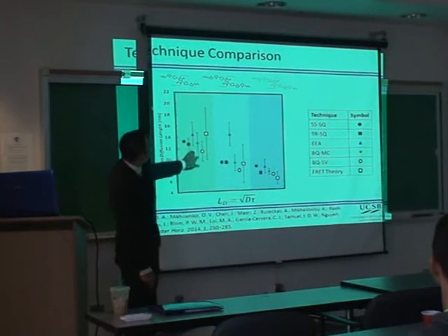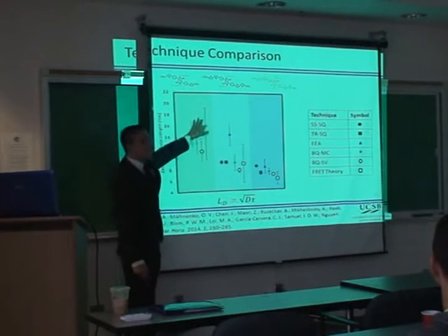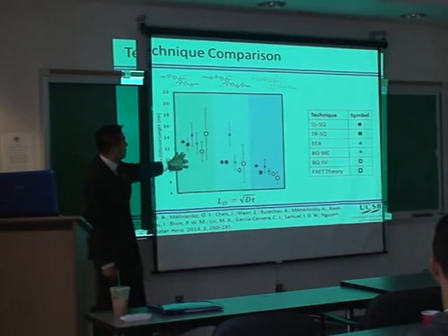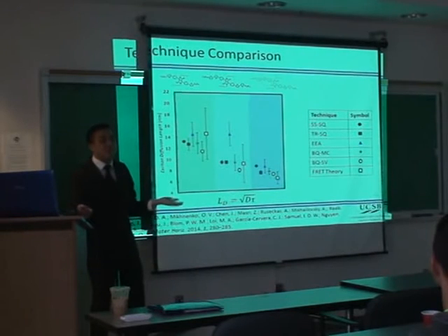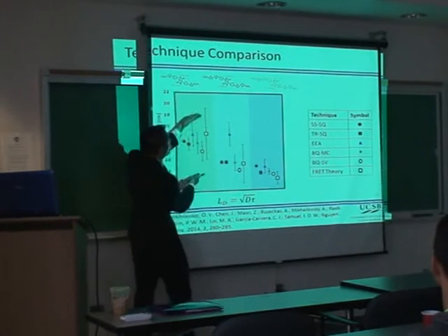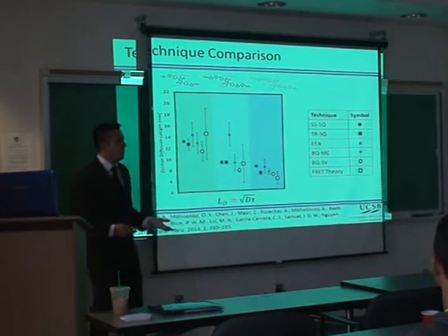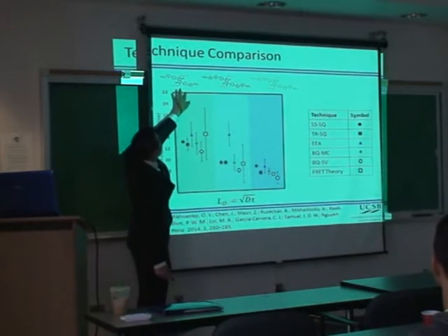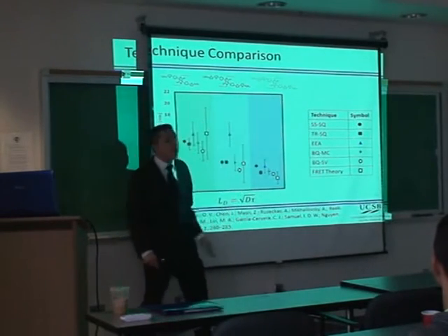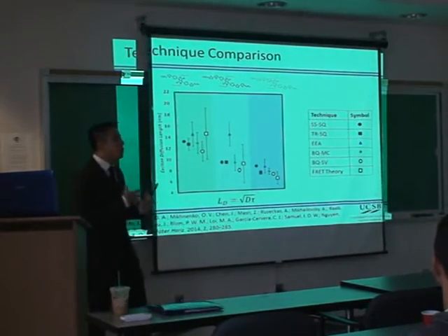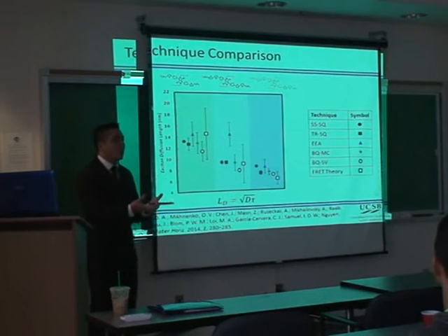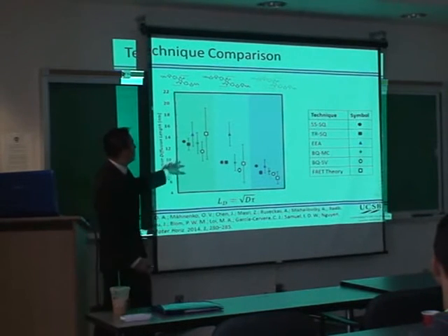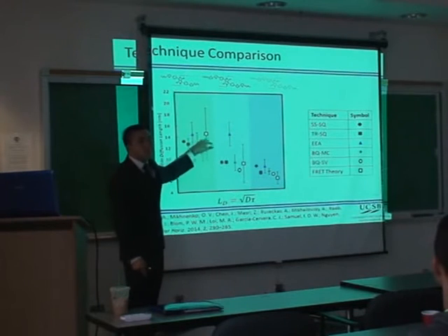But then, if you just look at this material here, the smaller one, now we get this larger distribution of exciton diffusion length. And this was very confusing. We have the same material, but we're getting different exciton diffusion lengths, and we're getting a larger error. The reason is that this material is very crystalline, a lot more crystalline relative to this one. This one's amorphous. And when you have crystalline materials, they're extremely sensitive to how you process them: how long you wait for them to dry, how fast you spin them, what the ambient temperature is. Anything to change that morphology.